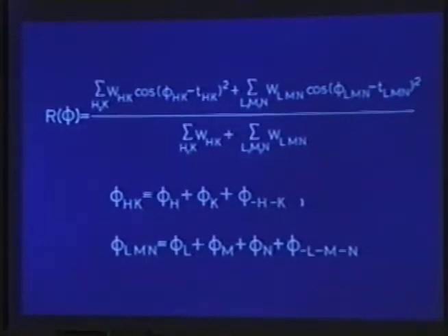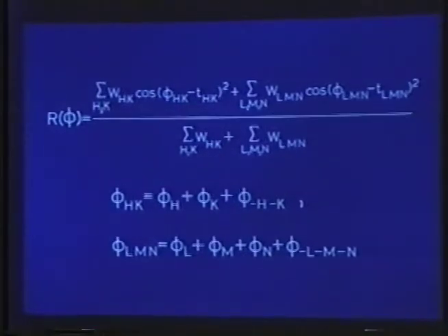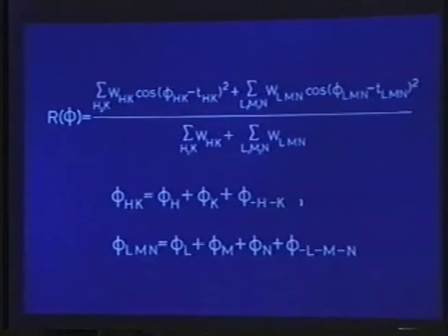As all of us know, the phases are things which crystals have and which crystallographers would like to get. But the phases are very slippery things because their values depend not only on the crystal structure, but also on the choice of origin. It is therefore necessary to introduce special linear combinations of the phases, the so-called structure invariants, which have the property that their values are uniquely determined by the crystal structure and are independent of the choice of origin.